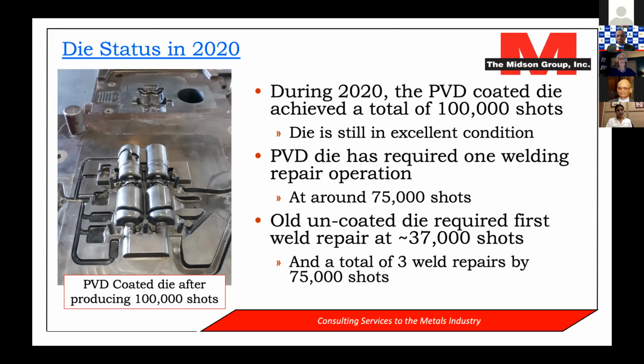shots. I should say that this PVD coated die has required one welding repair operation that occurred after around 75,000 shots. However, the old uncoated version of the die required its first weld repair around 37,000 shots, and had a total of 3 weld repairs by the time it got to 75,000 shots. So only one weld repair for the PVD coated die, 3 weld repairs for the uncoated die.